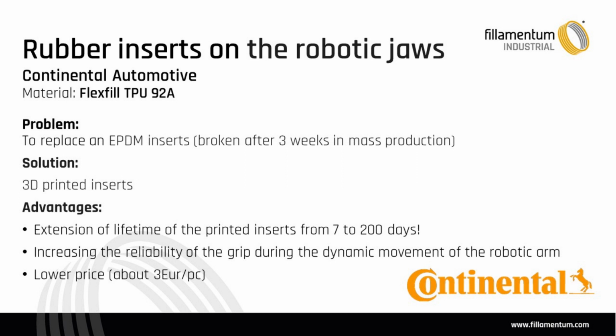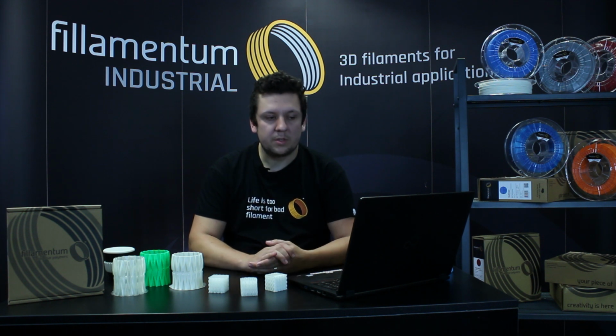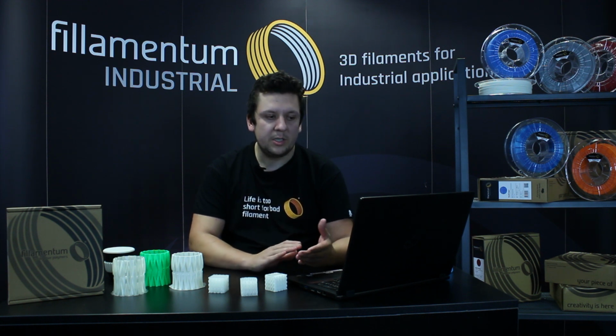Shore A. The original inserts were made from EPDM, and they broke after 3 weeks in mass production. So the main task was to extend the lifespan of this part. The solution was a 3D printed insert from our material TPU 92A. The advantage of this material is that it extends the lifetime of the inserts from 7 days to 200, so almost 7 months in production without any issues.